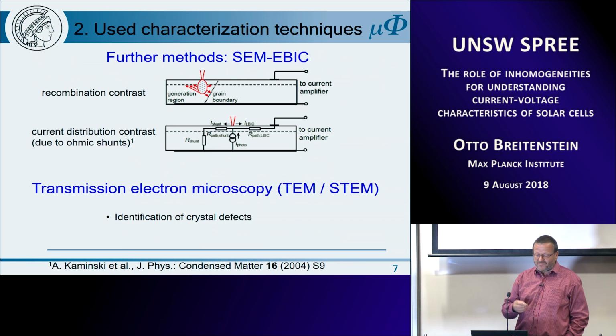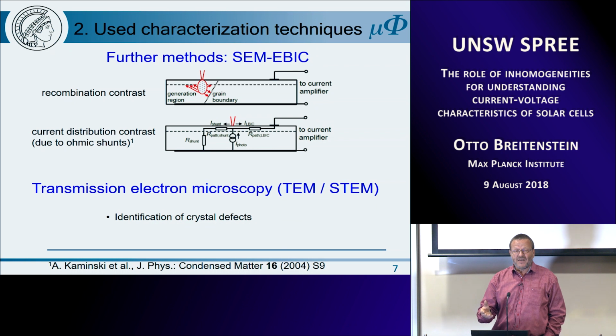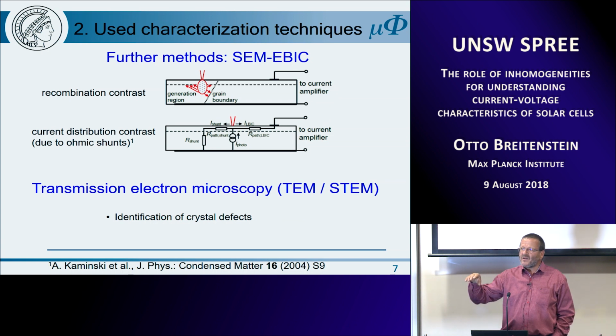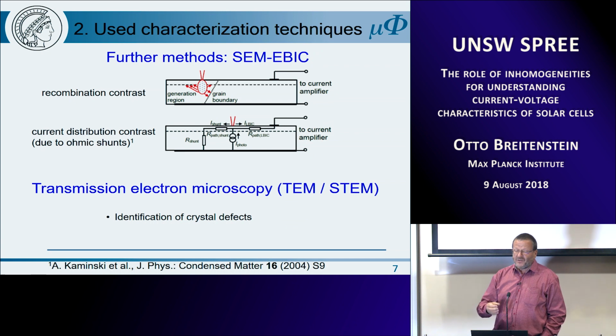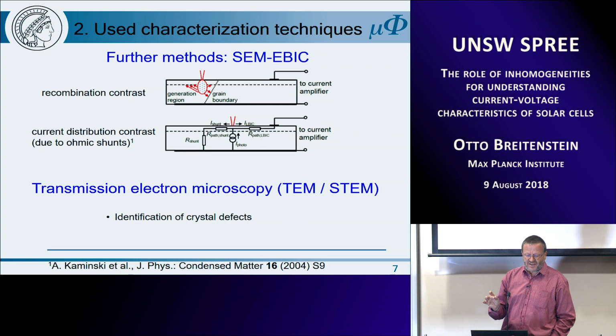Further methods we have been using was SEM-EBIC, which is physically very close to LBIC, light beam induced current. The difference is that in EBIC you do not have such a large penetration depth. So you investigate only the uppermost part, so you are not very sensitive to lifetime variations. So you need strong lifetime reductions to see anything. On the other hand, you have a much better spatial resolution because the electron beam can be focused much finer.